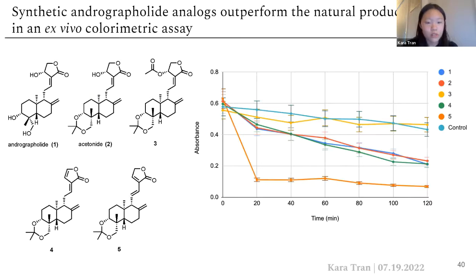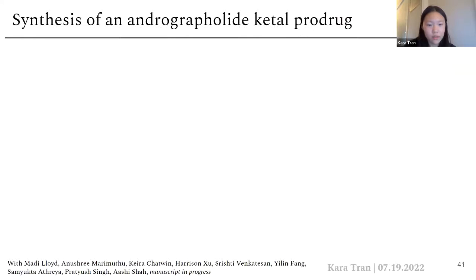These results were actually just recently published, and basically, to summarize it, consistent with expectations, andrographolide, which is compound 1 on this graph, and acetonide, which is compound 2, performed equally as well as Michael acceptors. However, compound 5, which was the 11-12 elimination product, was a significantly better Michael acceptor. Compound 3, which was with an acetate in place of a hydroxyl at C14, demonstrated the poorest Michael acceptor kinetics compared to the other analogs.